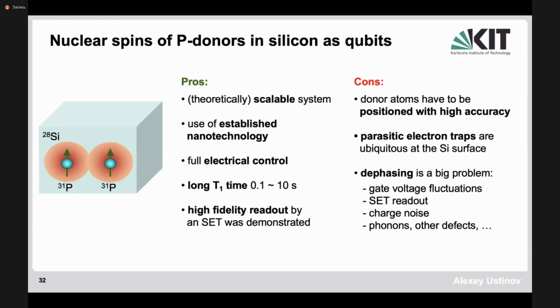And this parasitic noise really leads to small fluctuations of the fields around, and this in turn leads to dephasing. So one really has to use special pulse sequences, like, for example, the spin echo sequences, or maybe even high order spin refocusing pulses, in order to compensate for low frequency fluctuations. And of course, these spins are also subject to the influence of other defects, and the role of these sources of decoherence in large surfaces still remains unknown.